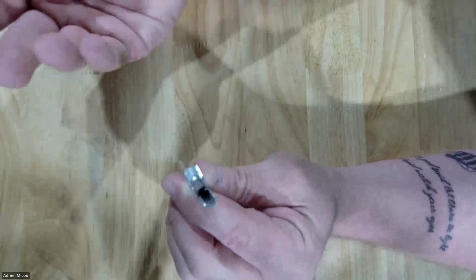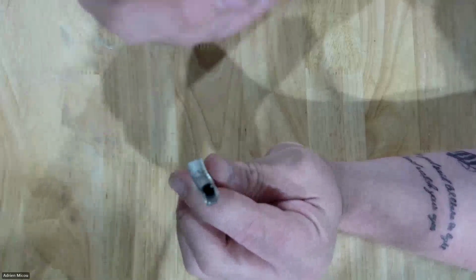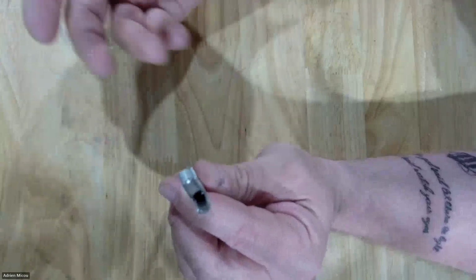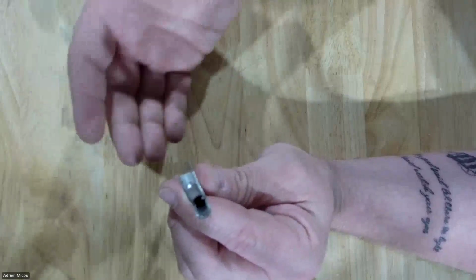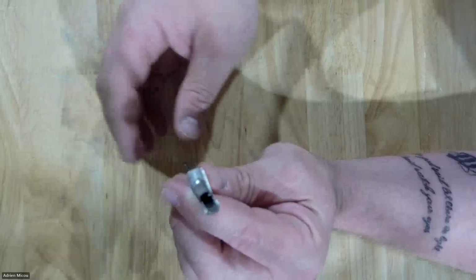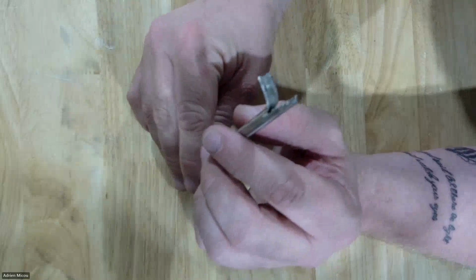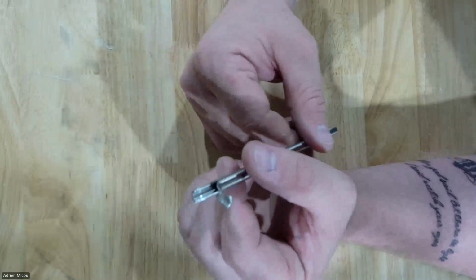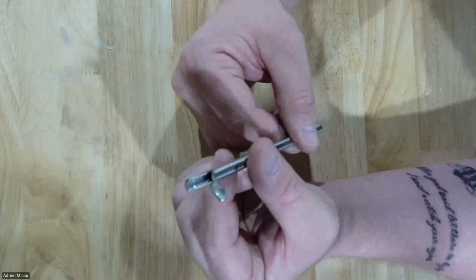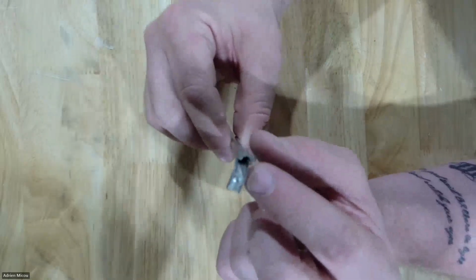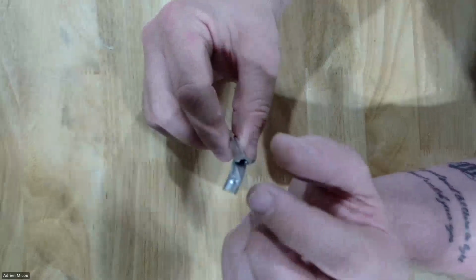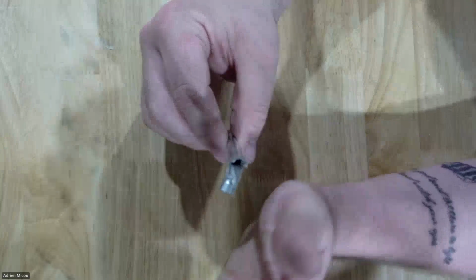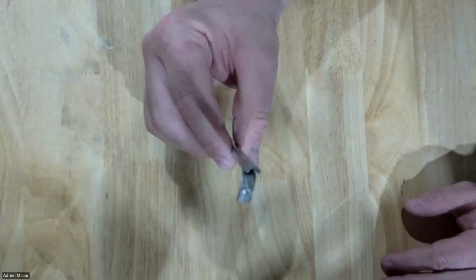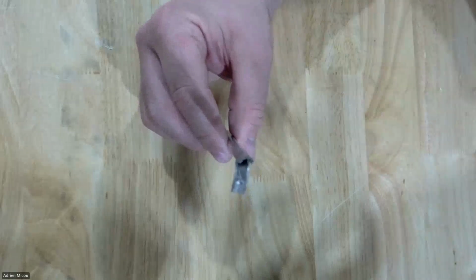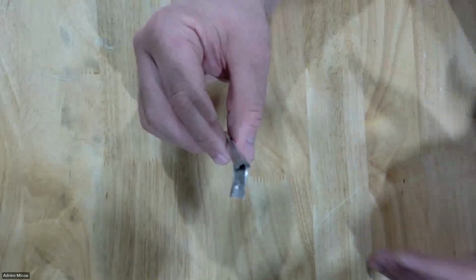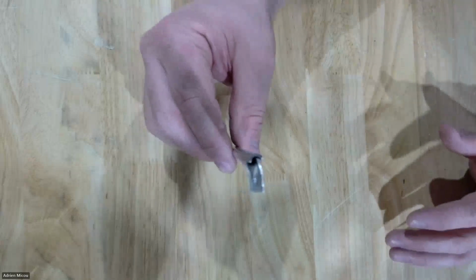And that's when we get more into developing the weld schedule and getting into those different levels, and where a canned program might not just necessarily work for you, that you have to actually have some understanding around what's going on in those different levels. So here you look, we have a pretty good ID bead width. Could have probably used maybe a little bit more adjustment, but for the purpose of this webinar. But you see, we also have no ID discoloration in here too. That's where that pressure and flow are very important. We also want flat welds where we're not worried about what's called convexity and concavity, right? We want flat welds so that the gas or fluids traveling through these systems don't have any restriction or cause any corrosion inside the tubing.